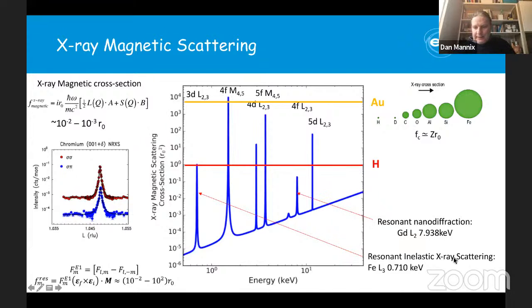However, for the resonant inelastic scattering, the RIXS data, which I'll show later on, we've been working in the soft X-rays and being able to tune into this very nice, strong resonance of the iron L edges.